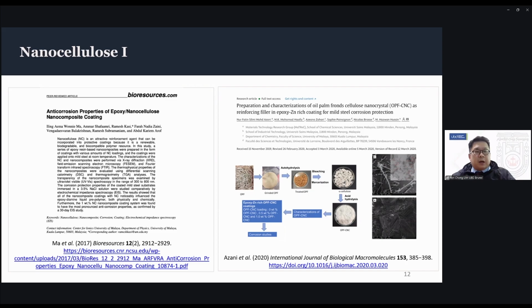Then incorporate this nanocellulose into epoxy. In this case, they focused on zinc-rich coatings to see if it can improve the corrosion performance of zinc-rich coatings. And actually, they did, and they linked the performance to the hydrophobicity of the cellulose nanocrystals that they produced.